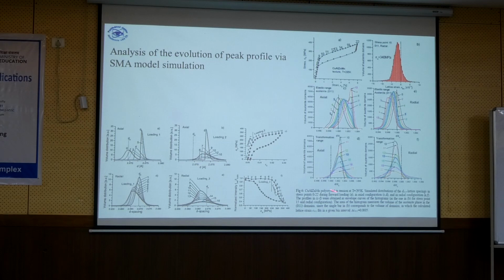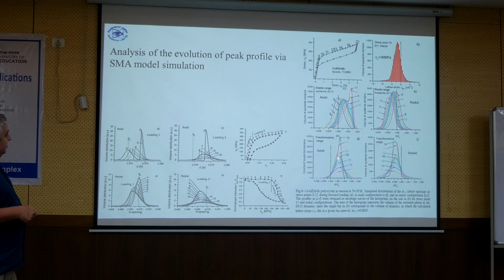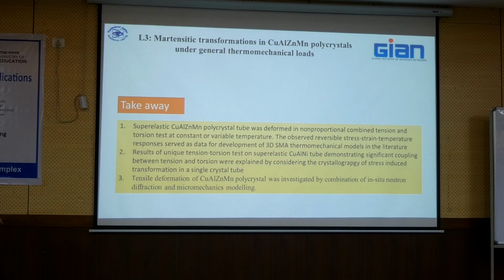So when we did the prediction with the model, we obtained exactly the same situation. In the actual, it's better seen. So at first the peak shifts until the point 10, and from the point 10 you have the decrease over here. So even the peak profile analysis very nicely could be reproduced. There is also the change of the peak width, but this is more related to the intergranular stresses between different materials.